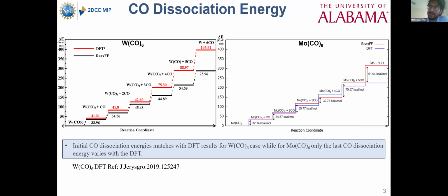And we compared the data with the molybdenum species, and we can see that for molybdenum, the DFT and the reactive potential matched well, at least for the first 5. For the last one, the reactive potential shows higher energy, but the DFT shows lower energy.